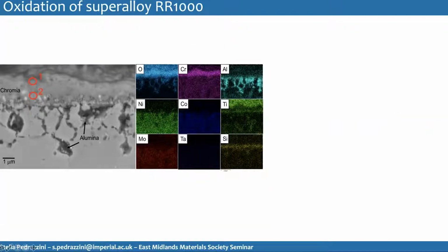And in this case, after 100 hours at 800 degrees, on the samples we formed the oxides that we expected. So we formed some chromia on the surface. There is a scale here that's mostly chromia. There is some rutile, so titanium oxide, on the surface. And there's a titanium enrichment at the oxide metal interface underneath as well. And then there are some alumina intrusions going on underneath. But this is based on SEM EDX.